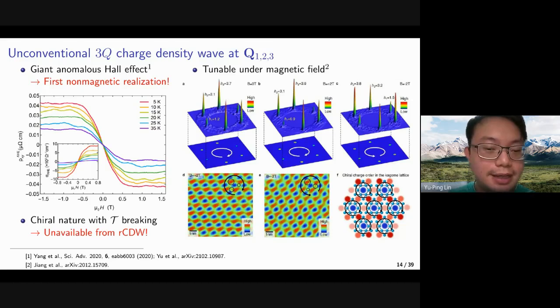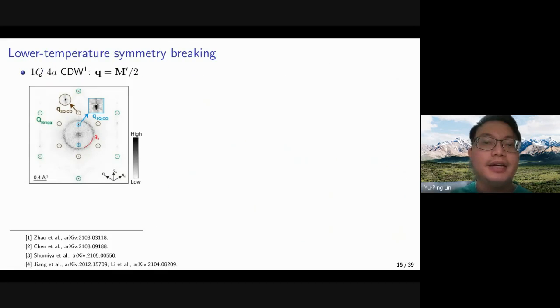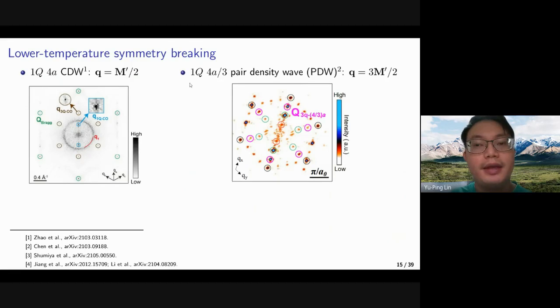So we should remember that this kind of time reversal symmetry breaking is unavailable from a real charge density wave. So we may want to look further at what could realize this kind of time reversal symmetry breaking. Also, it has been found that at lower temperatures, there could arise some 1Q order in addition to the 3Q orders. But now the wave vector is half of the 3Q orders, and the periodicity is four lattice sites. Meanwhile, there are also some additional pair-density wave proposals that were realized at the three-half saddle point momenta.